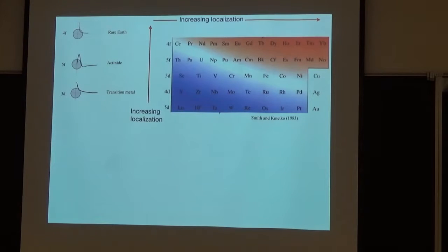And as Z gets larger, the radius of the D state or F state gets narrower. And so what happens is that all of these F electrons on the right-hand side here localize and form magnetic moments. The Hund's interactions lock them up together and make very, very large magnetic moments. And it's those magnetic moments that are so important to the new revolution in electric motors and magnets that occurred in the last 20 years. Because one of the great discoveries is that if you put anisotropic rare earth atoms inside iron, it converts it from a Heisenberg-like to an Ising-like magnet. And the Ising character of today's modern magnets means that they are much more robust and have much higher fields. And so that's one of the aspects of magnetism here.